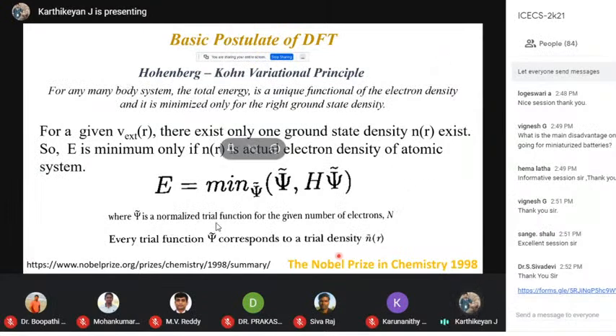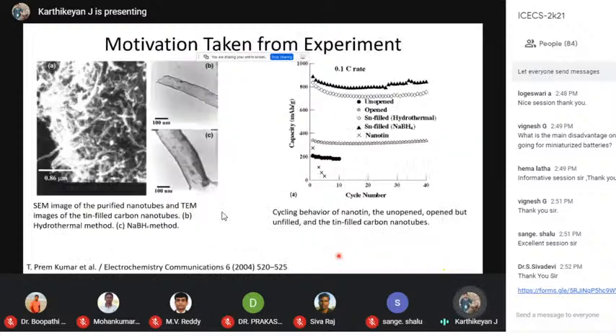So when you keep changing this density, you will reach a point in which the energy difference between the previous and next iteration will be very small. There we can stop. That means you have actually obtained the right density for your material. So we can actually get the energy. So that's how we can get the total energy of the system using density functional theory. And we are just going to use this for your atomic systems.